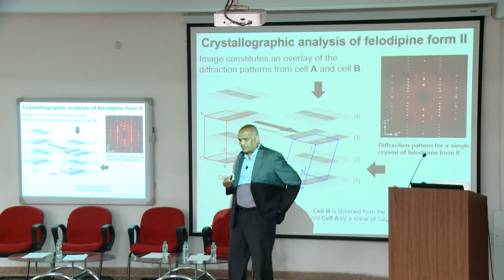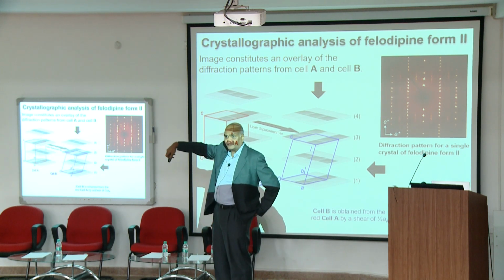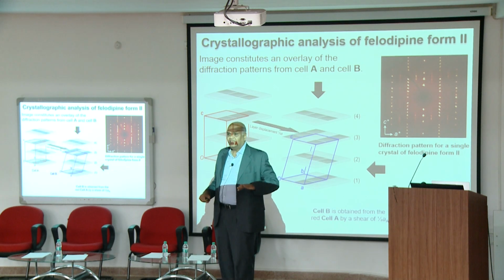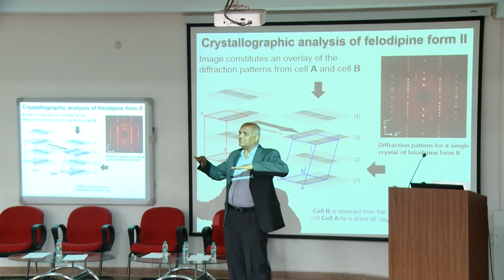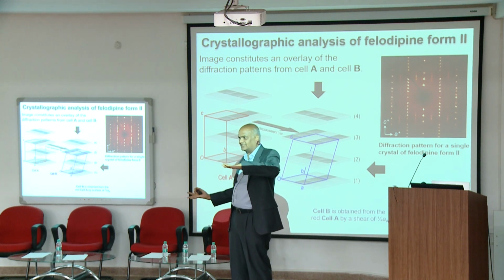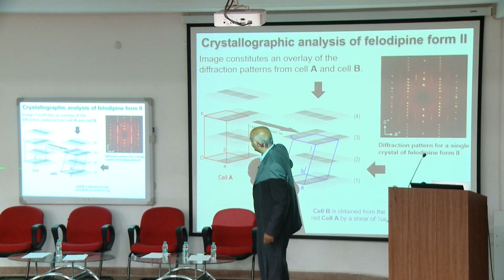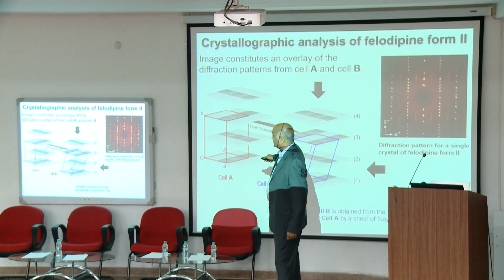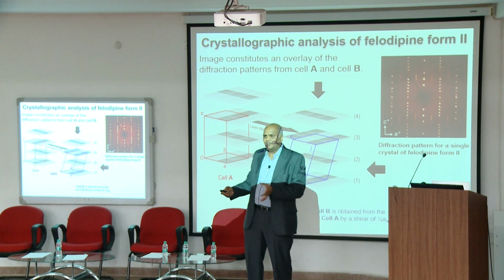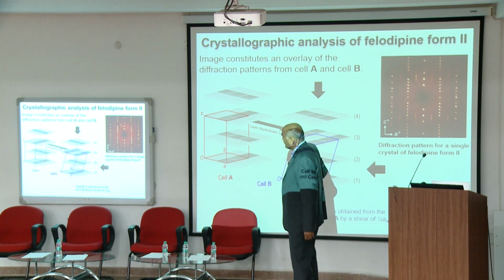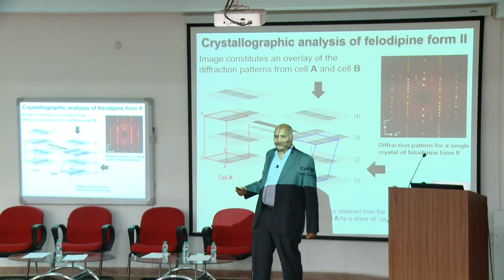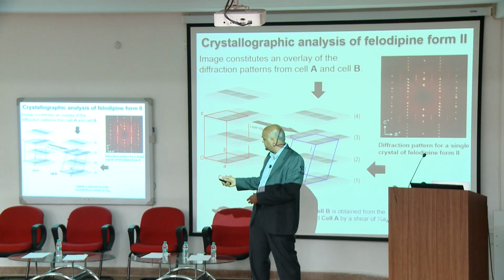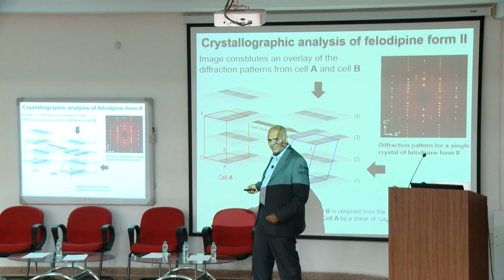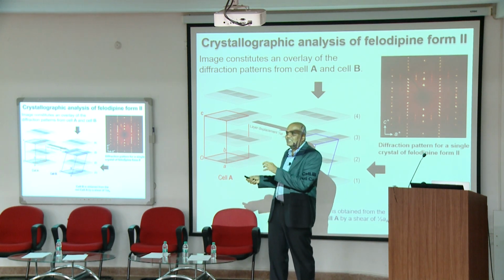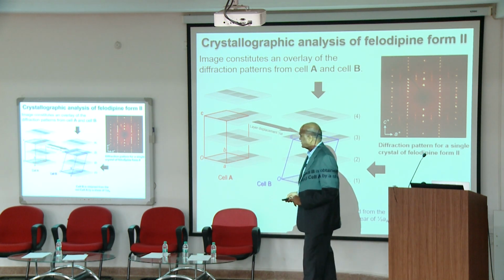So now let me just tell you this. If you were to indent these crystals from the top, the indenter will not be able to recognize which is what, because the structural difference is different from this direction, right? So if I poke it from the top, I should get some sort of a distributed response. But if I poke it from this side, if I am indenting on a region which is cell A, I will get one response. If I am indenting on a region which has a cell B structure, I will get a different response. So this is what we hypothesized, and we went ahead and looked at it.